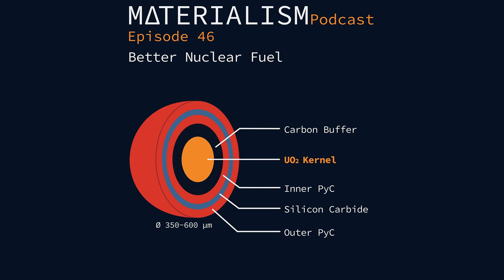Okay. So for our porous low-density pyrocarbon, they basically decompose gaseous acetylene, which when it deposits will form this very porous 50% theoretical density pyrocarbon. To get that thicker, denser layer, they actually use a mixture of acetylene and propylene.